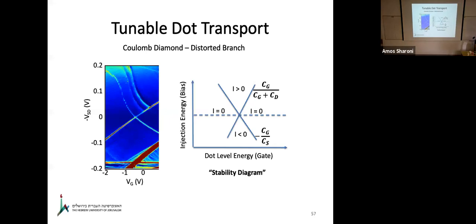To show you the features of your dot, you use a normal-insulator-superconductor junction, and then you have to filter out the density of states of the superconductor. Not always, because why don't you use normal-insulator normally? I can, because for the benefit of sticking within my time limits, I didn't show you data where I actually do that, but because you asked the question, you are going to be punished by looking at this data.